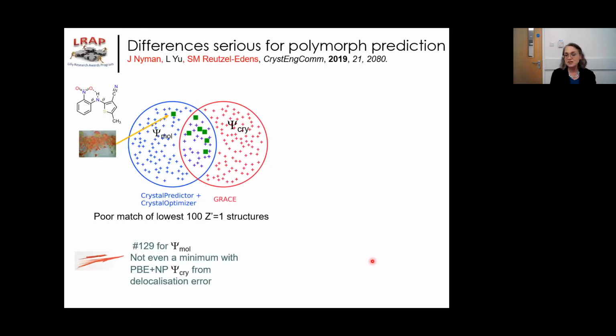So Eli Lilly have the advantage of being a company that could engage both with a commercial company who could do crystal structure prediction for industry, and these are my collaborators' predictions for Roy. And they just looked at the overlap between the top 100 one molecule in the asymmetric unit structures for this molecule, and the overlap is embarrassingly small. We do get most of the experimental structures, though our method got Roy, but embarrassingly, there is another polymorph that is outside the top 100 by our method and isn't even a minimum on the electronic structure method that was being used for this.